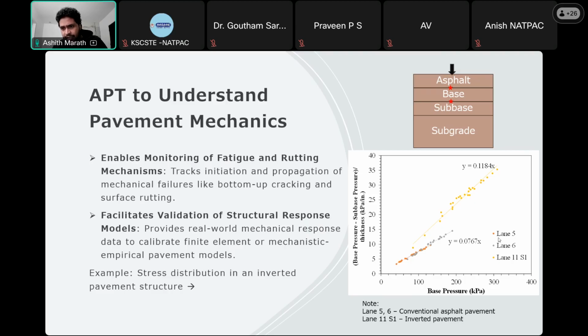The legends are lane 5, 6, and lane 11. Lanes 5 and 6 are conventional asphalt pavement, with the same pavement structure except for the type of asphalt mixture used. One has a polymer modified binder, and the other has a conventional asphalt binder. If you look at these plots, the data points are the pressure values. The y-axis is the difference between the vertical pressure at the base and sub-base layer. Here you can see the two star dots; that is the location where we measure the vertical pressures. The y-axis shows the difference between these pressures divided by the thickness of the base layer.